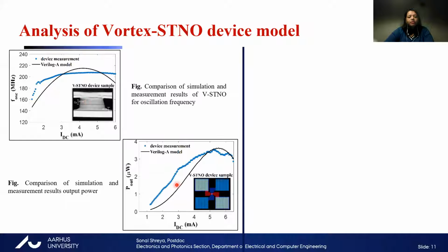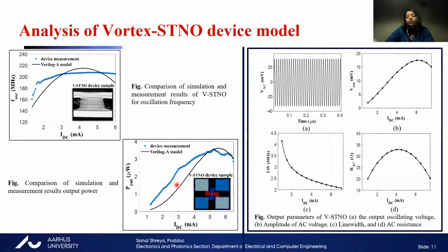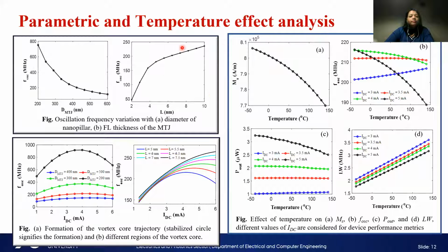So this is the oscillation frequency, and this is the output power. These are several other parameters, for example the AC voltage, the line width, and the AC resistance. If we go for parametric and temperature effects, then depending on temperature, all these parameters get affected. It is interesting to note that with reducing nanodisk diameter, the frequency will be higher, but of course there will be other problems that we need to face. If we increase the free layer thickness beyond the exchange length, it helps in forming the vortex core, and the frequency also increases.